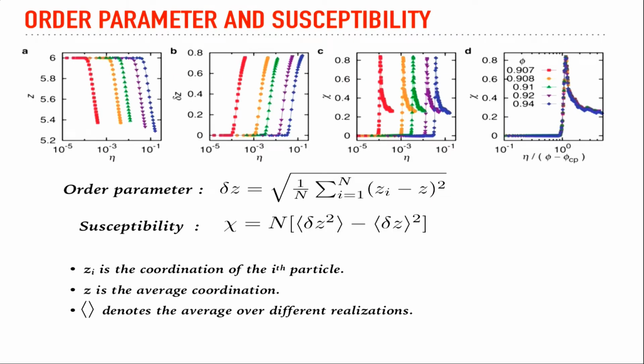And this transition is characterized by some very strange hidden variables, as was described in that study, but it has some interesting properties. For example, as you increase the polydispersity, the contact numbers vary quite smoothly. This is the average coordination of the system. It starts from 6 because all particles have 6 neighbors, and then as you increase polydispersity, the number of contacts start to break, and these are for different overcompressions. So if it's very highly overcompressed, it takes more polydispersity for you to start breaking contacts.